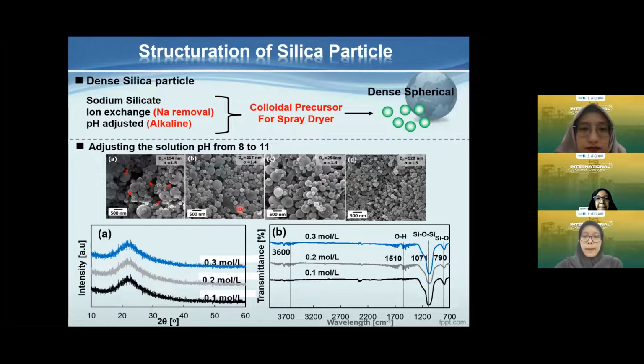And then how about the crystallinity of the silica particles? Because silica is an amorphous material, there is no significant peak in the XRD result, because this is just silica and there is no composite here. And then how about the FTIR result? It also confirms that the silica particle was successfully produced, because there is a significant peak at around 1071 here. So this is the silica particles.